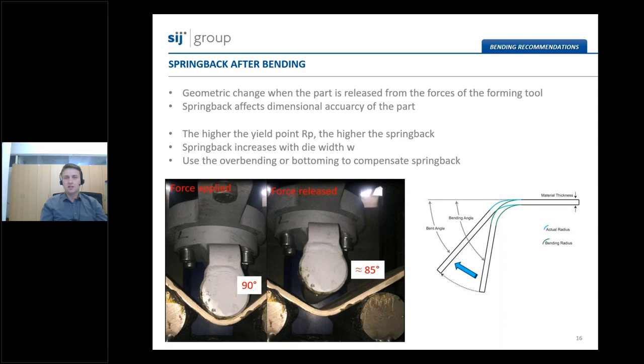It is hard to exactly define how to overcome this problem. We, as the steel producer, can only give you some instructions, let's say. Mostly people in the workshops use the so-called overbending. It means that if you want the final angle of 90 degrees, you should overbend to approximately 100 degrees. And please note that spring back and overbending angles should be practically tested in your workshops, because this phenomenon also depends on the tools used for the bending in each particular workshop.